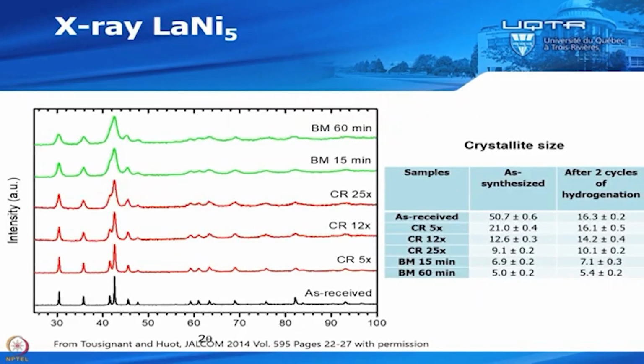So this is the diffraction pattern. So as received, cold roll 5 times, 12 times, 25, and ball mill, and you see that at 15 minutes of ball mill, the peaks are already quite broad compared to 5 cold roll. The peaks are broader, but not so much. Okay, so ball milling is much more efficient to reduce into nanocrystalline structure, and you see it here.